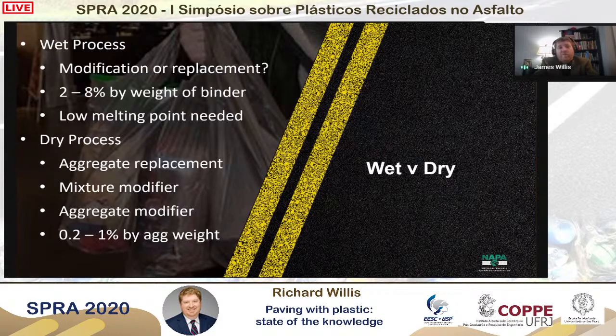In the US, the primary distress that we see is cracking. And binder quality and quantity are two very important parameters that impact the cracking resistance of an asphalt mixture. As we start talking about taking binder out of our mixes, are we going to then drive that cracking performance down and make our mixtures not perform?